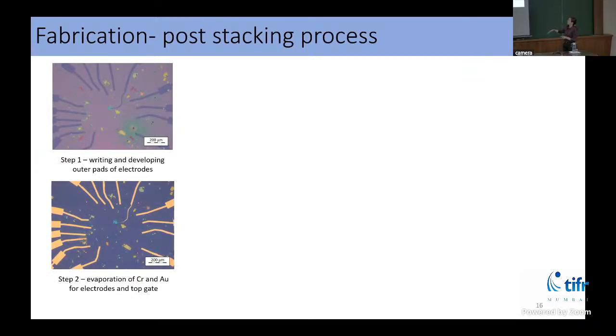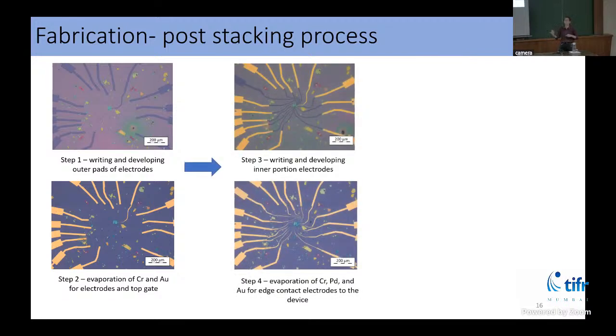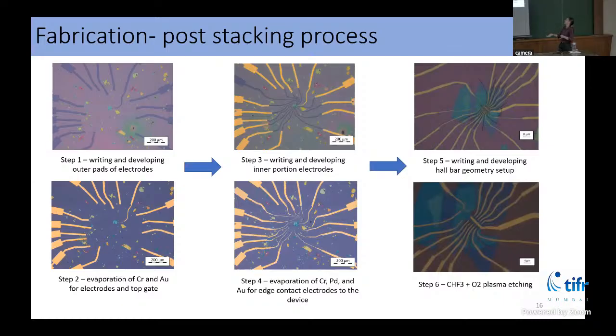So now I have a stack ready, which is this blue thing inside in this picture, but now I want to measure the electronics, so I need to make electrodes to it. There is a post-stacking process of lithography and evaporation of metals where I make the contacts, and the final device looks like this. The motivation for this geometry, a Hall bar geometry, is that it allows me to measure resistances not only in the direction of the current, but also in a perpendicular direction. So I am able to get longitudinal as well as transverse resistances and infer different physics from that. It is called a Hall bar because I can get transverse resistance, which is the Hall voltage.